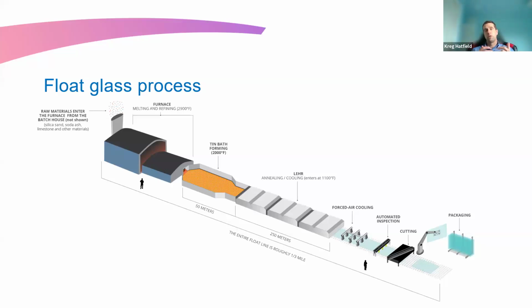And then there's what we call attenuators on each side to make sure the glass doesn't crook around the furnace, the tin bath, that it actually goes straight down the line into making the thickness of glass you want inside there. So we can make either really thin glass, up to 2.33 millimeters, up into about 15 millimeters in thicknesses on these float lines. The current ones in the US make roughly, the thickest glass we can make here in the US right now is 12 millimeters or half an inch thick. So this is the process of manufacturing glass from start to finish.